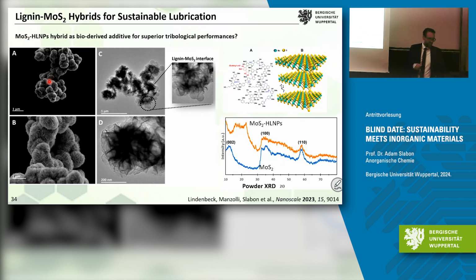Here you can see the control - these are pure MoS2 nanosheets. You can see the 2D structure, and then we grew it on the lignin inside. I really like this interface image - this is the lignin nanoparticle interface with the 2D material. Chemically speaking, this is your interface.